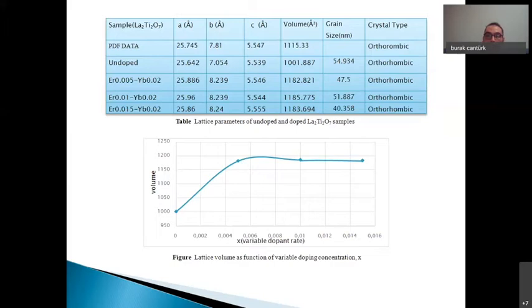In comparison with the undoped, co-doped phosphors showed bigger unit volume, since the addition of the rare earth ions into the crystal structure leads to an increase in the values of the lattice parameters as well. But there was no simple pattern between the volume and the doping concentration. I mean, volume did not increase steadily with the rising doping rate. In here, it's erbium, of course, but thus it leads to slight distortion in the lattice.